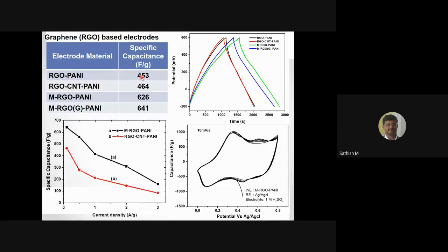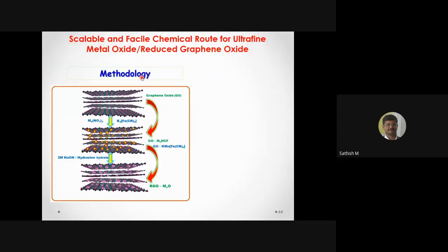So because of this, we observed that this polymerization has a major role. So we extended this technique for other cases. Like this case, we make a graphene oxide. We make a metal hexacyanoferrate complex. You put metal ions and potassium ferricyanide, and you can make a metal hexacyanoferrate. When you decompose this metal hexacyanoferrate with sodium hydroxide, you can directly end up with some metal oxides.